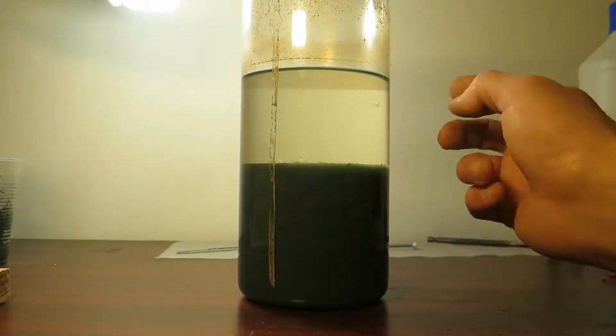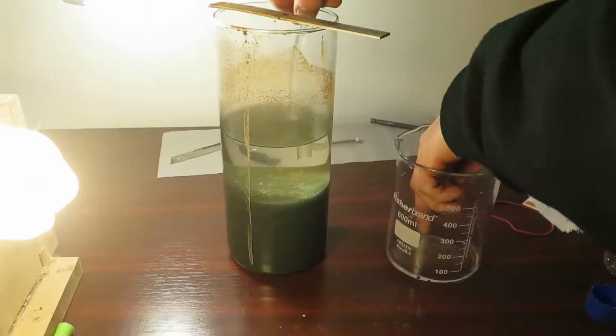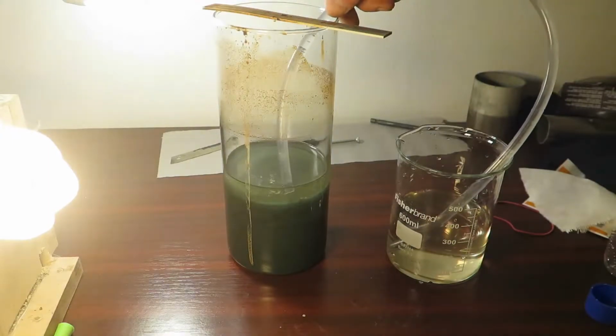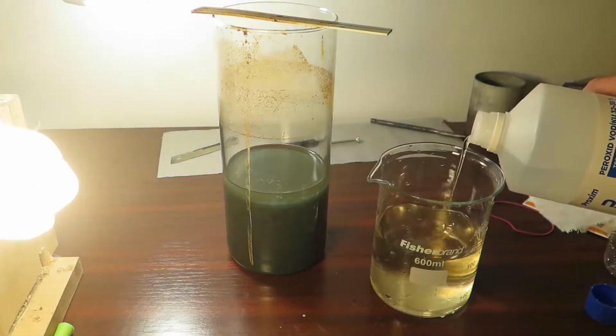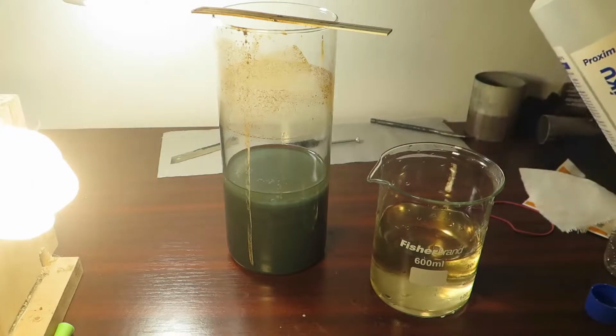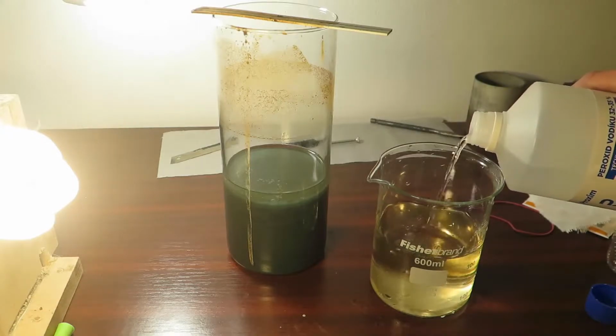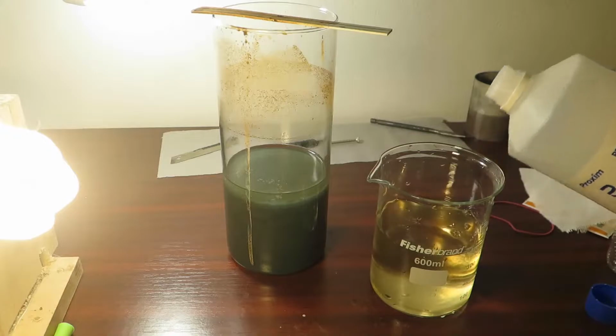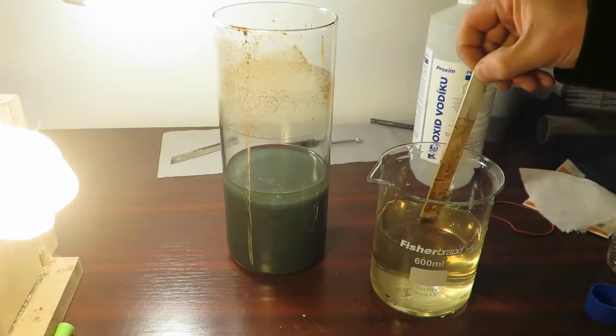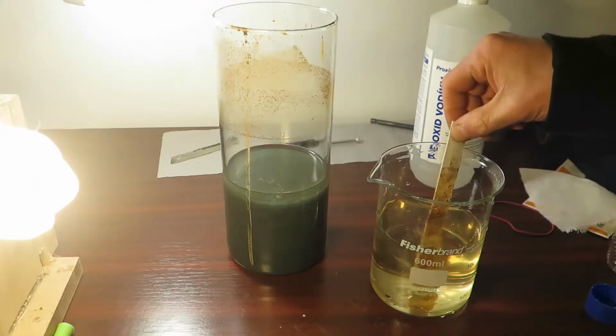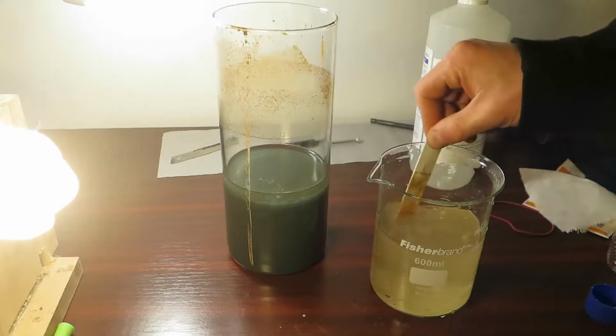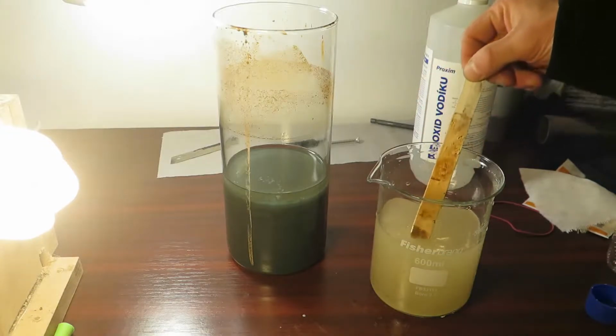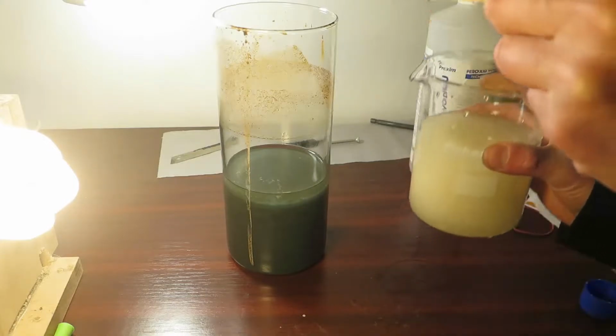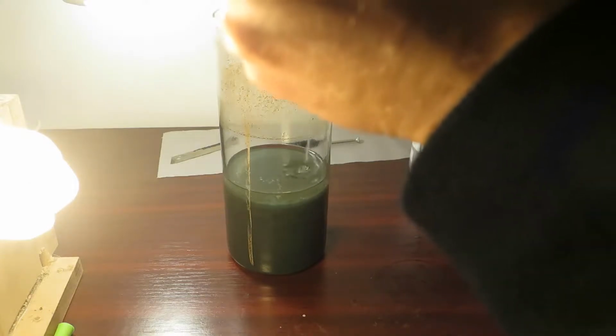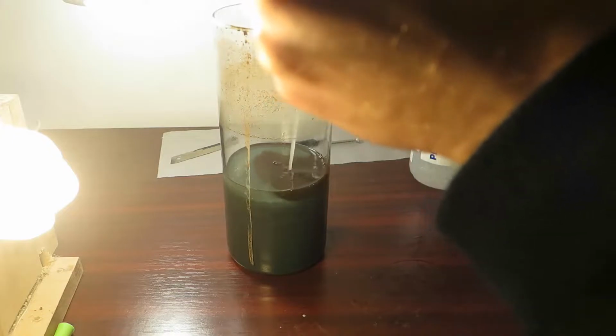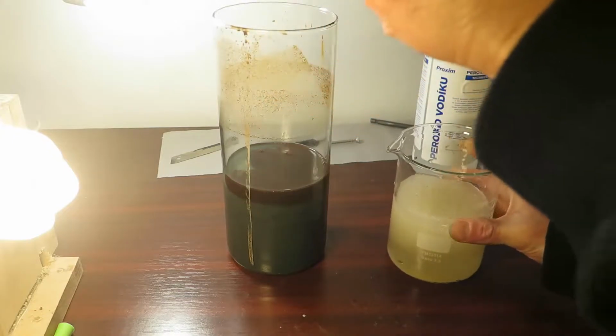After the precipitate settled down, I siphoned the remaining liquid into another container. Then I added some hydrogen peroxide to this liquid, assuming that it contains only some sodium salt, so nothing happens. And that's true, nothing has happened, so good. Anyway, the point is that I'm trying to dilute the hydrogen peroxide, because in the next step I expect quite a vigorous reaction. Okay, so I slowly poured back the hydrogen peroxide solution, and it wasn't that bad actually.